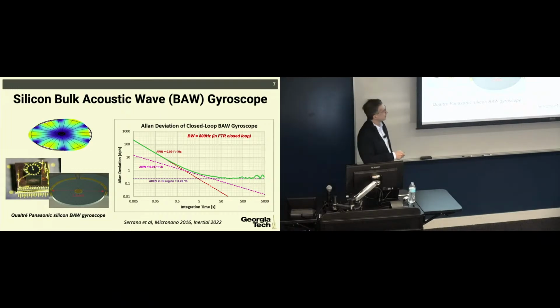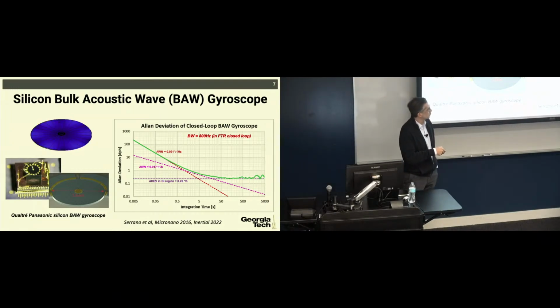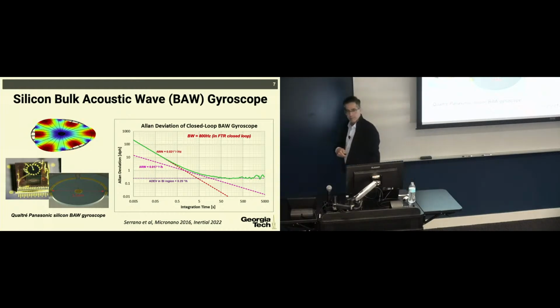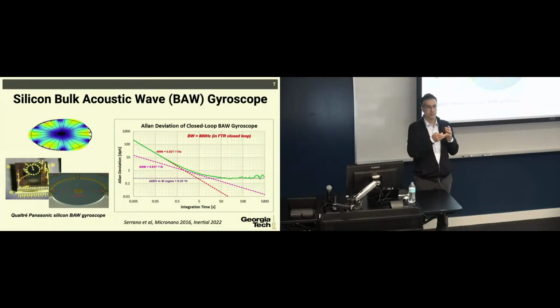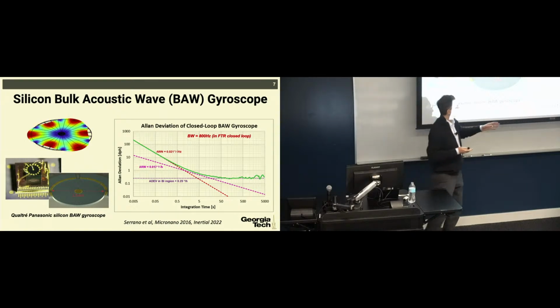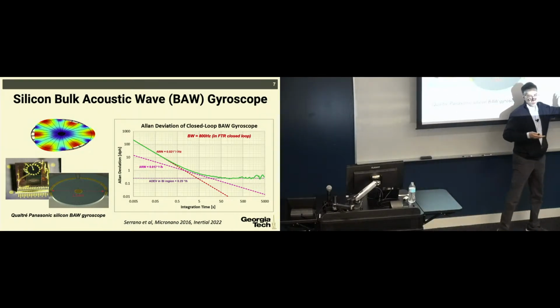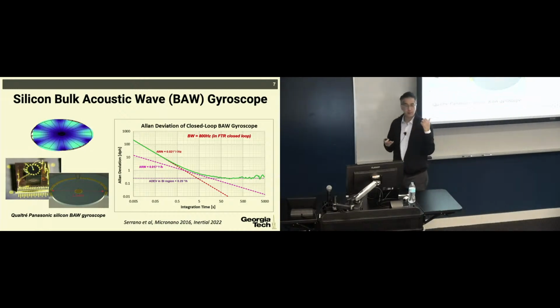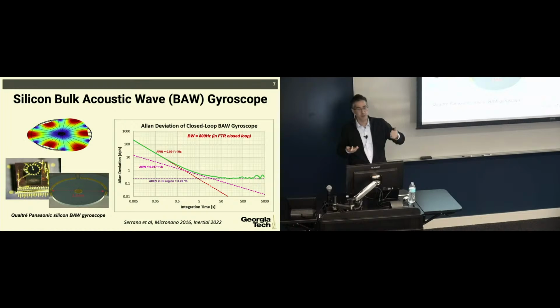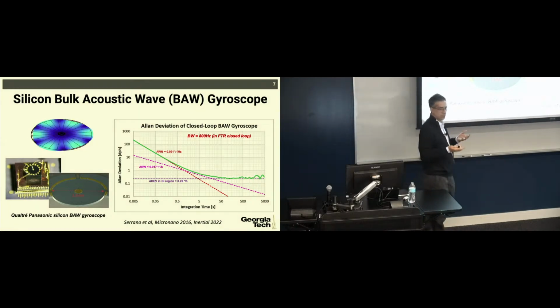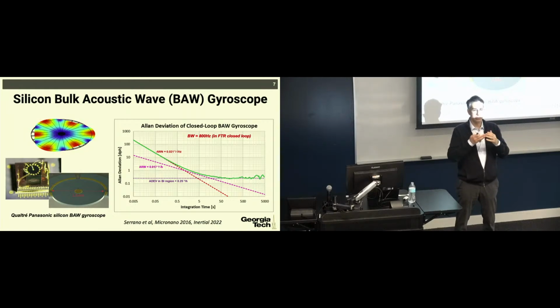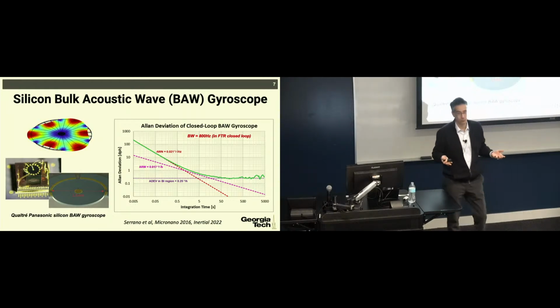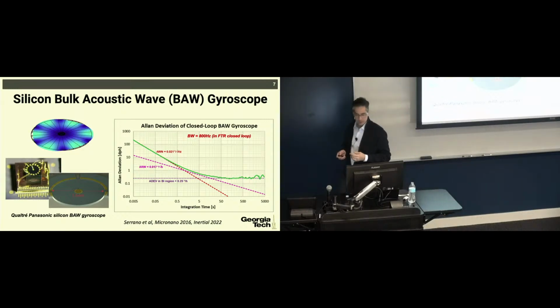So this device now has a bias instability, or best noise performance, of about 0.2 degree per hour. And just as a frame of reference, the Earth rotates 360 degrees in 24 hours, right? So the Earth rotation rate is about 15 degrees per hour. So this is easily a couple orders of magnitude less than the Earth rotation rate. So you can actually measure the Earth rotation rate with this device, and you can do what is known as gyrocompassing, which is detecting the true north instead of using a magnetometer to do compassing. So there are a lot of cool things you can do with gyroscopes.